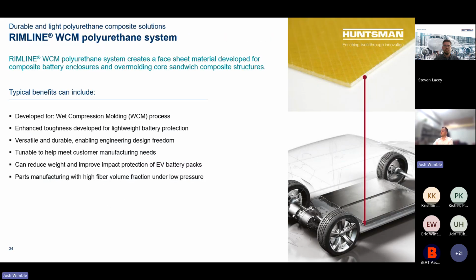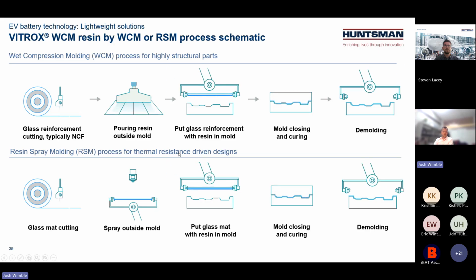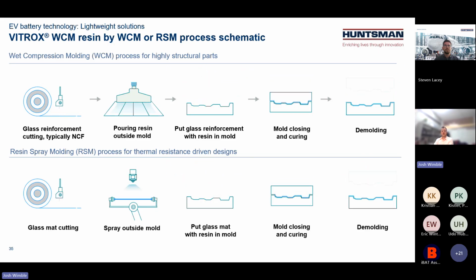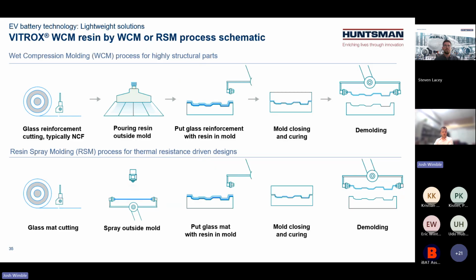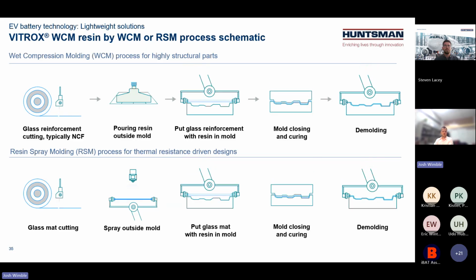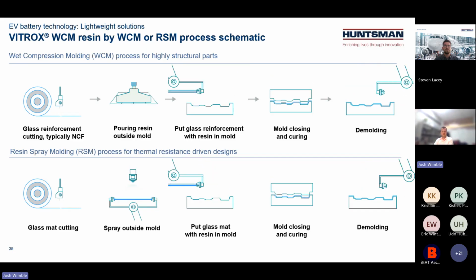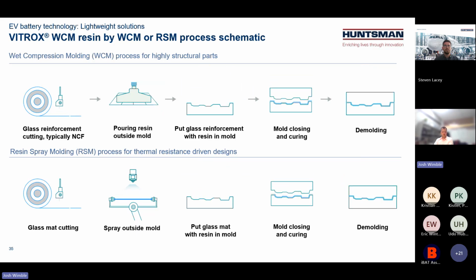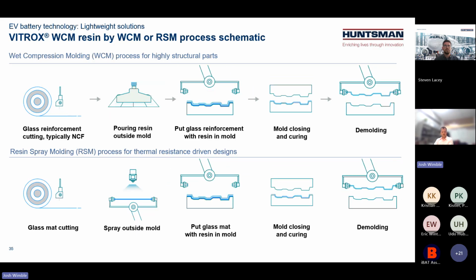So first I'm going to describe the skin part of this sandwich panel. Our polyurethane is suitable for a wide array of processing conditions. Here, I'm going to talk about wet compression molding used in the protection of these underbody shields. So first, let me start with explaining wet compression molding. You can use our polyurethane technology in resin transfer molding and resin spray molding, which are already used in many roof and floor composites in automotive. It's ideal for flat, simple parts. And then wet compression molding, which is mostly what I'll talk about today, is recommended for underbody shields and lids.